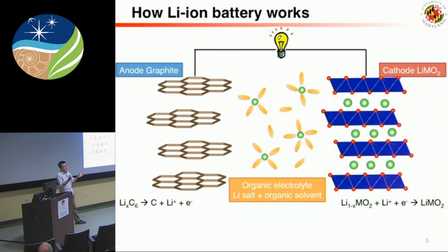What kind of defects cause the degradation? Oh, you mean the commercial ones? Okay. It's complicated, in the sense that anything can fail, and anything that fails will give you a problem. For example, in this electrode material, here is a simplified diagram, but in real material you have a particle, and you have to coat it, and make it a composite in the electrode. Over time, one thing is that this particle may break off from the electrode, so it either does not get lithium or does not get an electron. That becomes dead material.